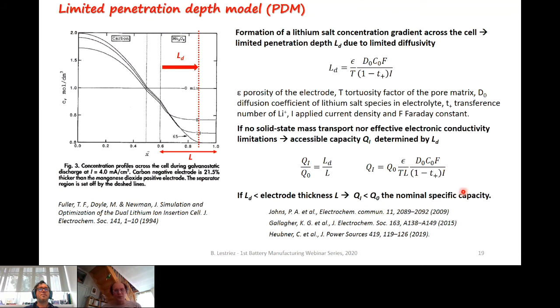So now I would like to address this limited penetration depth model. It accounts for the formation of the lithium salt concentration gradient across the cell, which is illustrated here. This is a plot from a pioneer work by Fuller, Doyle, and Newman, where you see the lithium salt concentration at the beginning of discharge and during discharge, and you can realize here that at some point of the discharge, the lithium salt concentration has dropped to 0 at the bottom part of the electrode. That means this part of the electrode cannot further proceed with the electrochemical reaction because there is no more available lithium for insertion. And if you go to higher rate, this area will appear sooner during discharge and will also be of larger size.